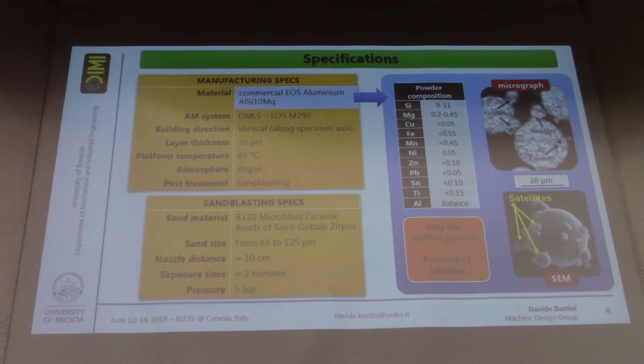Here are the machining specifications of our specimen. Specimens were vertically built with a little preheating on the bed. Specimens were then manually sandblasted with ceramic beads. The powder is the commercial powder by EOS, and as we can see, the composition is pretty standard.